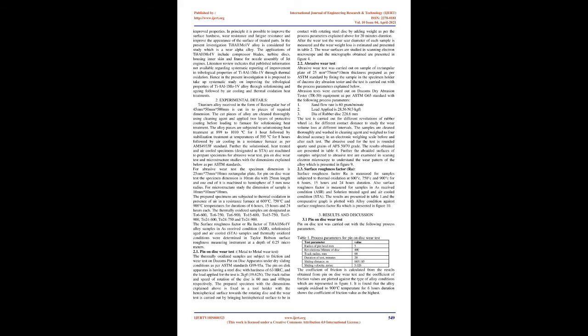and nitro-oxidizing. The thermal oxidation process is one of the most important advances in the field of surface engineering of Ti-based materials due to its capability of enhancing the tribological properties of Ti alloys. Ti6Al4V alloy treated using thermal oxidation exhibited low coefficient of friction and low wear rate, which is attributed to both the formation of a useful oxide and hardened diffusion layer.